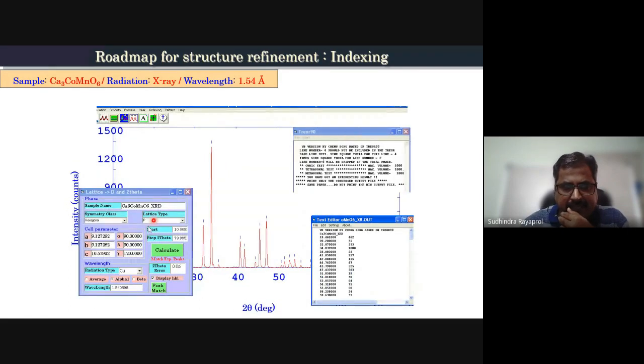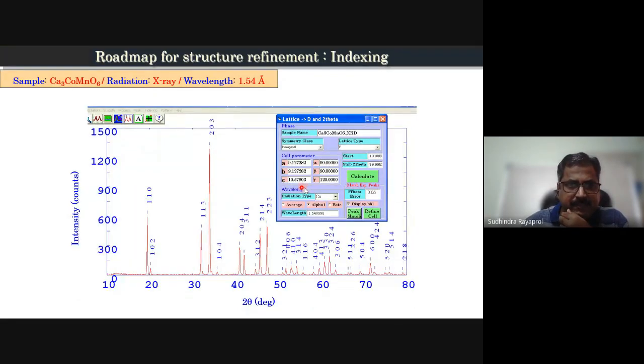Depending on the quality of your data, it can give you some suggestions like what symmetry class it has and what the possible cell parameters are. Using these initial values, you can carry out the indexing of the peaks, and it will define the cell parameters also. It requires initial cell parameters and the HKL and D positions of the Bragg peaks to generate the list of HKL and D values. Once you calculate and do the peak match, this is the information you get, which means that you can index all the Bragg peaks, and at the same time you can refine the cell parameters.